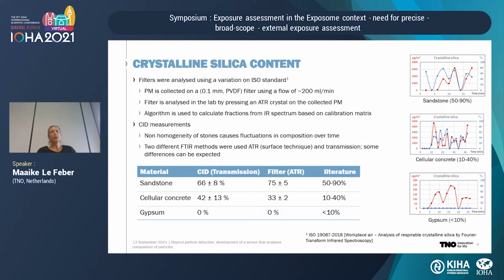So in the table below, you can see the different crystalline silica content of the materials as established by the different methods. So sandstone with the CID as well as with the filter measurement has obviously more crystalline silica than cellular concrete and then gypsum, which is in good parallel with what literature reports on the crystalline silica content of these materials. As you can also see, the CID measurements are not identical to the filter measurements. That is something that we didn't expect because 2 different methods are used. So the CID makes use of a transmission method, while the filter was assessed using ATR, which is a surface technique. Both are FTIR methods.